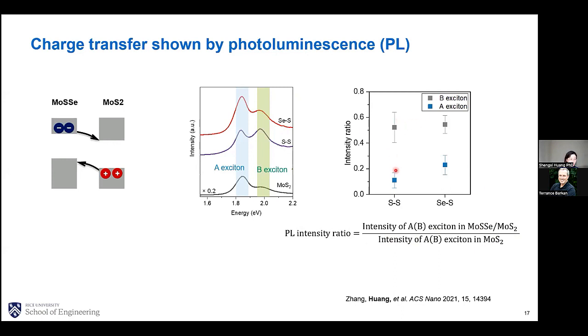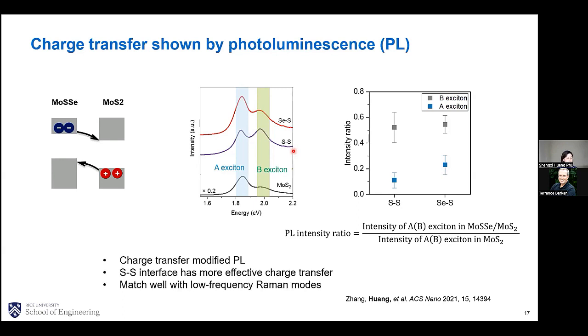So we can see the intensity ratio calculated over here, especially for the A exciton. The intensity ratio is much smaller for the SS interface compared to the Se-S interface. And this is because of a more effective charge transfer in the SS interface, due to the stronger interlayer coupling strength. So this result matches very well with our low frequency Raman modes.